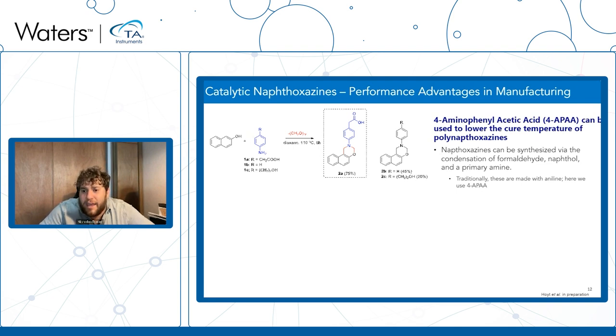So here we can take this 4-aminophenylacetic acid, and we can make our own naphthoxazine out of it. And the big difference is it has this carboxylic acid, which might lead to enhanced performance. So one of our postdocs, Caroline Hoyt, made a bunch of these materials, and she showed that she can make this, and she can make the petrochemical-based naphthoxazine, and then she could cure them and make materials.